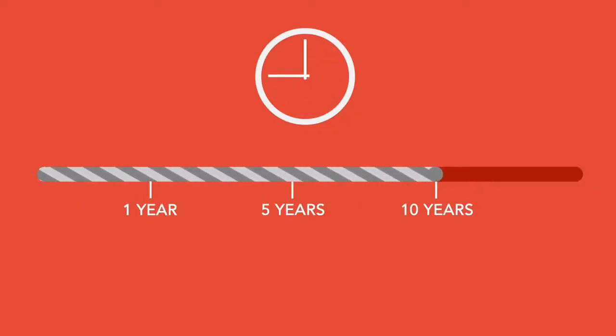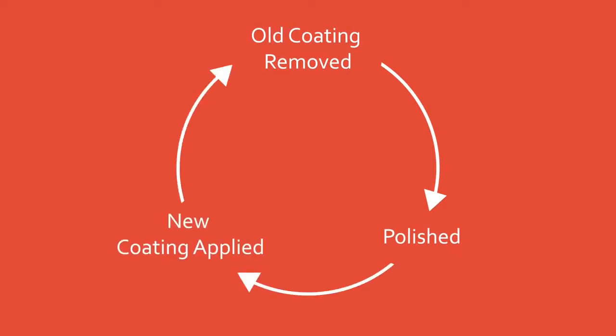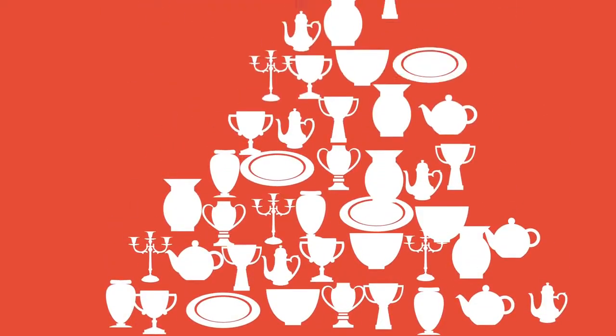The best way to protect your silver is to apply a coating. And currently, museums use a plastic coating that lasts about 10 years. At that 10-year mark, the coating has to be removed, the silver polished, and a new coating applied. For museums with thousands of silver objects, this creates a nearly constant cycle of damage and recoating.